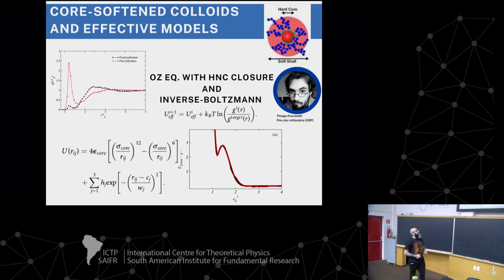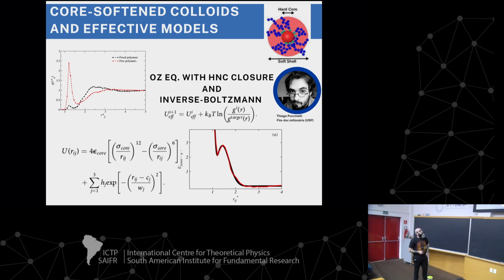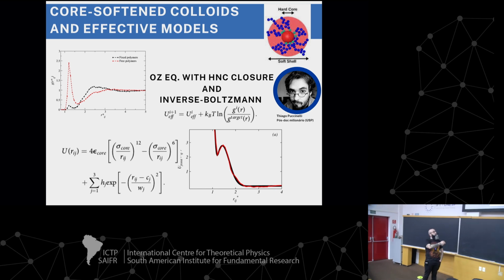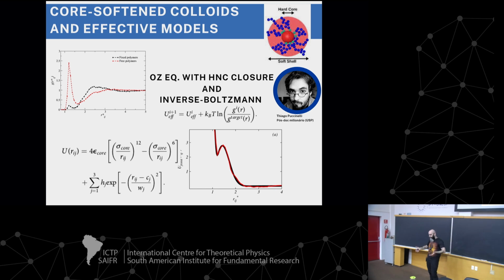So this was the inspiration for a work that we did a few years ago with the contribution of two former students. One of them is Thiago, who is now a postdoc and, well, making more money than myself with the FAPESP scholarship. But we took this kind of model and made a coarse-grained model, so it's not an atomistic simulation. You basically pick a bigger sphere in the center, put a lot of polymers around it, run a lot of simulations, and evaluate the g(r).